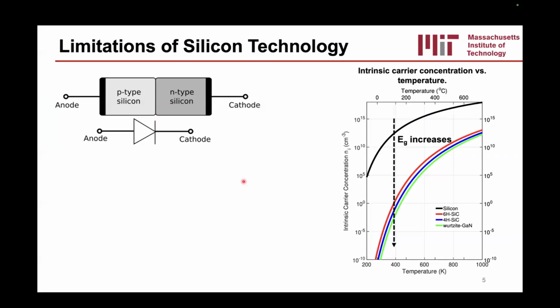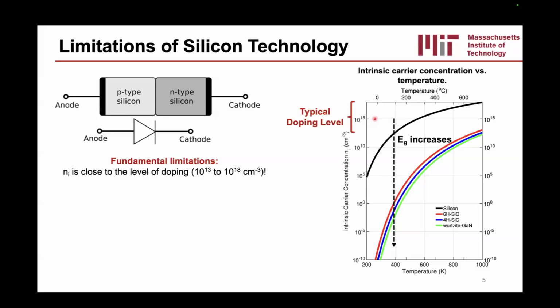Turns out silicon just can't provide the solutions we need at these high temperatures. And that's almost at a fundamental level. Most silicon devices operate on this idea of a p-n junction. However, that starts to fail once the intrinsic carrier concentration, or the background level of the silicon or semiconductor, gets to really high temperature, because this intrinsic carrier concentration increases exponentially with temperature, as you can kind of see in this black line here. And for silicon around 200, 250 Celsius, you start getting into the 10 to the 15 range, which is around the range of typical dopants. And so all your p-n junctions end up just as kind of resistors. And so you can't make a rectifying junction, you can't make a switch, you can't make a transistor.